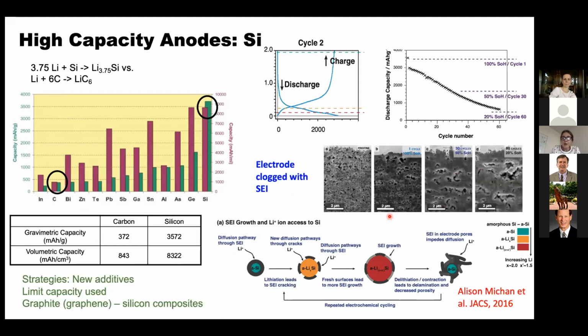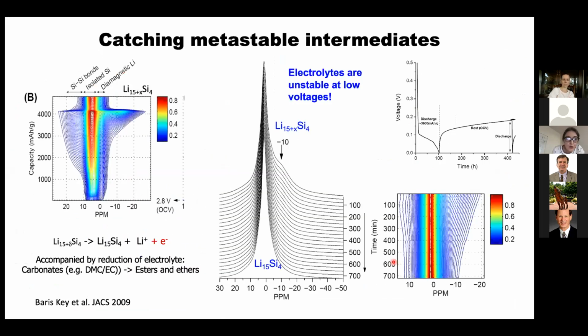But the real problem is the silicon expands and contracts, and as it does, it exposes fresh surfaces and the reaction continues. And so that's why silicon still can't be cycled for more than 200 or 300 cycles, unless there's a strategy such as limiting how much you cycle, or maybe adding graphene, or looking at various composites. And again, happy to talk more about that later.